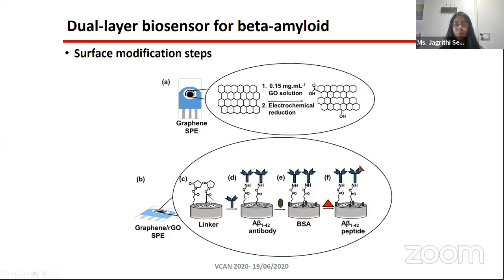The linker that we used here is called 1-pyrene butyric N-hydroxysuccinimide ester. It's a non-covalent linker, and the reason for using it is because it forms pi-pi stacking on the RGO. Therefore, it will not have any adverse effect on the conductivity or electroactivity of your underlying RGO or graphene structure. And the next step is the immobilization of antibodies.